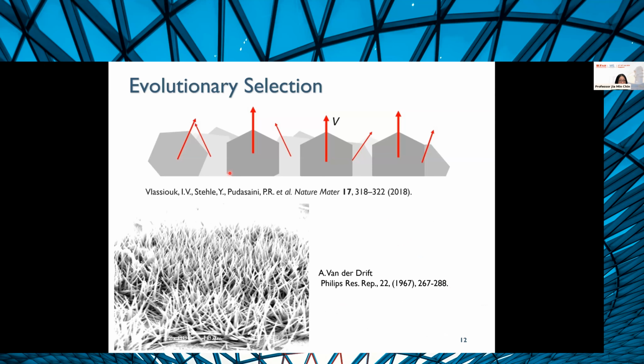So what is evolutionary selection? Simply put, let's say you have some crystals on a substrate and they're growing out. And let's say the big red arrows are their fastest growing direction. If these crystals happen to be growing with their fastest growing direction vertical, whereas you have some neighboring crystals that happen to nucleate with their fastest growing direction not vertical, or let's say even worse, horizontal, then very rapidly these crystals start to see their growth inhibited because they grow into their neighbors and then their growth is blocked. So what ends up happening is that you start to select for crystals that happen to be growing vertically in the fastest crystallographic direction of growth. And so in this case, you have a very dense growth that selects for this vertical growth of these nano or micro needles.